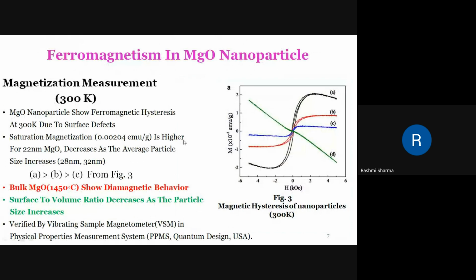So now we move on to the ferromagnetism in magnesium oxide nanoparticles. This is the magnetization measurement, which was done by using a vibrating sample magnetometer. For a ferromagnetic material, the ferromagnetic hysteresis is a characteristic property. In this plot, these are the ferromagnetic hysteresis curves for nanoparticles of different sizes and for a bulk material. A represents the 22 nanometer magnesium oxide nanoparticle, B represents the 28 nanometer nanoparticle, C represents the 32 nanometer nanoparticle, and D is for the bulk magnesium oxide sample.